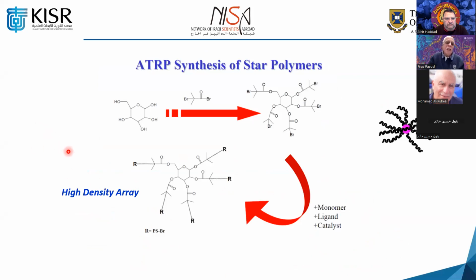We started initially looking into surface grafting, etc. But then we started looking into developing some sort of a star type of branch polymer. We use such a compound, and then we attached an ATRP initiator to it, and then we start different polymerizations from that, and you build up a star with a controlled molecular weight. Here we use polystyrene, and we built it in.